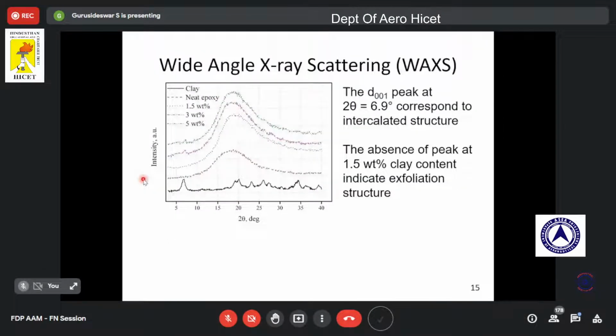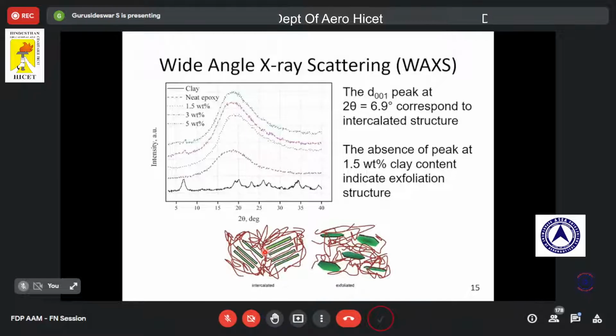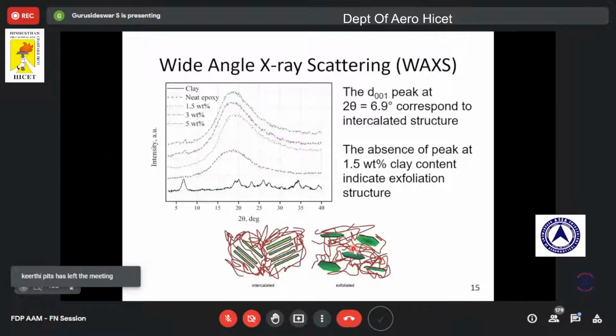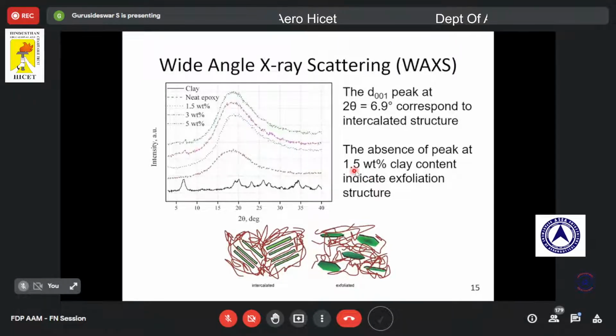Here I have given the pictorial representation of the different structures. So you can see the intercalated structure. We do not see a good dispersion. The clay has been arranged in some parallel fashion. It's in a bit of an agglomerated stage, whereas on this right-hand side, the exfoliated structure, the clay has been dispersed randomly. So this is what we want, and this dispersion we have achieved at lower clay loading, say 1.5% clay loading. Here I just wanted to show the different magnifications of raw clay. This left-hand side micrograph shows low magnification. It is around 23,000x.